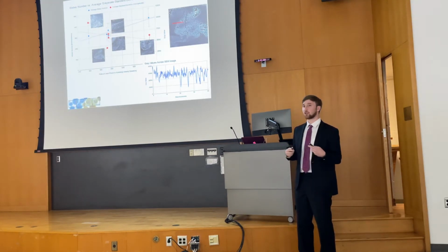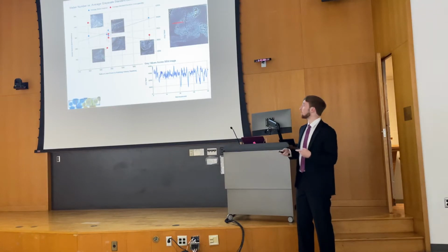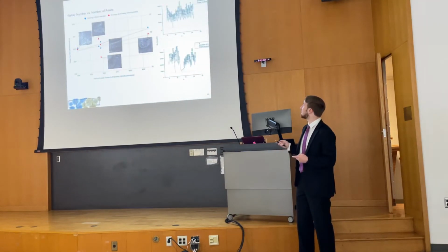However, this doesn't tell the whole picture, because it could be well mixed and still have a high standard deviation if you had dendritic structures where it was well mixed. So the second method was to look at the number of peaks, because if it was well mixed, you would have consistent peaks throughout, whereas if there was a point that was more aluminum or more tin heavy, it would have an inhomogeneity like this. And graphing that, we found a similar trend where there was increasing Weber number associated with an increased number of peaks. And this is, of course, graphed relative to the ratio of laser power to scanning velocity.